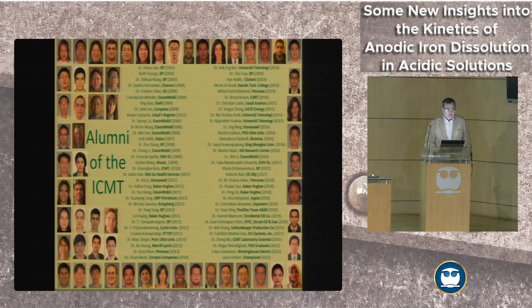So what my student did, I'm going to do it in chlorides. And she got a slightly bigger semicircle, which is no big deal, believe it or not. That's a detail. You can make the circles the same size. What matters is the number of these loops, these semicircles. So there's this one here and there's that one there. And this one happens at 20 hertz, this at 40 hertz. That must be the same thing. Frequency is the same, the shape is the same, that's got to be the same process. So no difference in this process when it comes to chlorides versus sulfate.